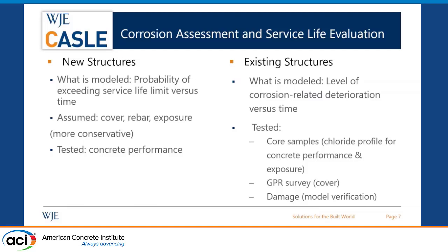Working with new structures involves making some assumptions. For example, for concrete cover, we assume distributions based on construction tolerances because we don't yet know the as-built conditions. Sometimes we also assume different types of rebar, and based on the results, we can decide which type of rebar would be appropriate to achieve the service life requirement. We make assumptions about exposure as well, and we test concrete performance to inform our model.